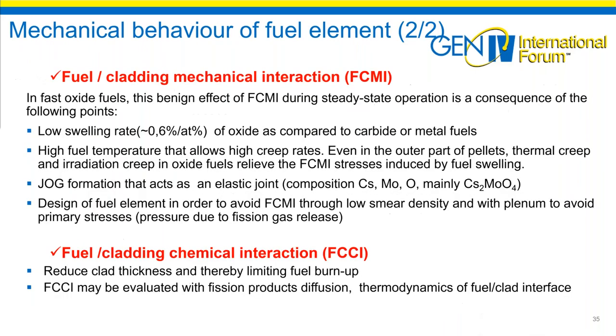So next slide, please. Still on the mechanical behavior, we have seen that we have two main mechanical phenomena observed. The first is a clad-pellet mechanical interaction, which is controlled by a relatively low oxide swelling rate due to high fuel temperature, which by thermal creep leads to non-rigid behavior towards the structural material. Also because of the JOG formation that acts as an elastic joint without a stress transmission.